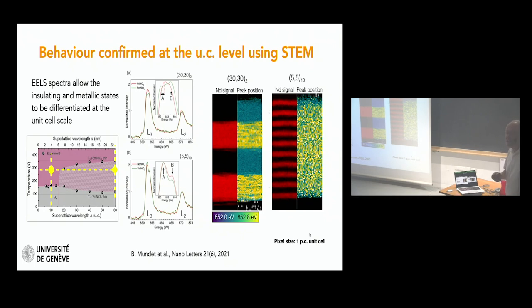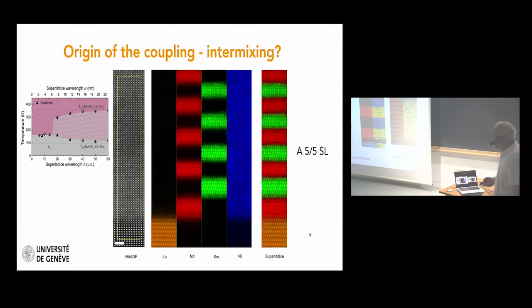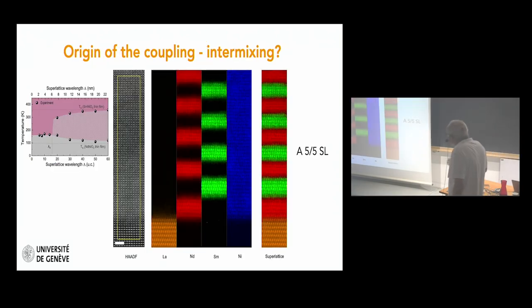So now, what is the origin of this coupling? The first thing we wanted to rule out is intermixing, because obviously if you have a lot of intermixing, at some point you have a solid solution, and you have a single transition. But what we saw through scanning transmission electron microscopy, again on a 5 unit cell sample, is essentially no intermixing in the system, with extremely abrupt interfaces, as you can see here.